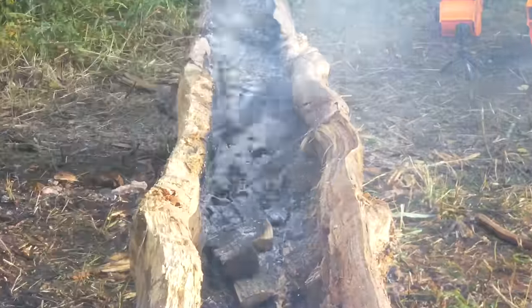So far, I've experimented with trying to use clay molds that have been left to dry for various lengths. Assuming it was the residual moisture in the clay, I figured firing the clay would solve the issue. And Annalise made a test mold of a bell to test it out on. However, the result of that cast still had issues with voids forming in the cast. For help finding the historical method used for the molds, I reached out to my Discord and was directed to some research that revealed the answer was right in front of me the whole time. Cob. Or at least an explanation of what makes cob a good heat-resistant material.